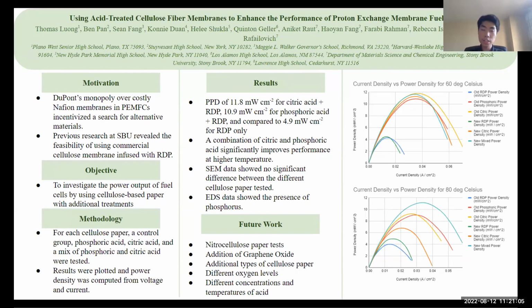Our results show that acid treatment was effective on all types of cellulose paper we tested and produced a power output double that of the control group. Additionally, we found that mixing citric and phosphoric acid can improve performance at higher temperatures. We did SEM analysis, which shows that there is no significant difference between the chemical compositions of the different cellulose papers. And finally, through EDS analysis, we found phosphorus, which indicates that RDP was successfully infused into cellulose paper.